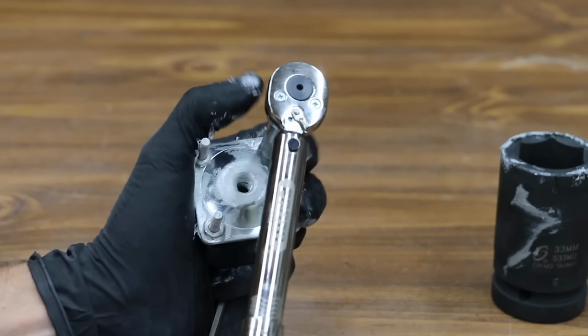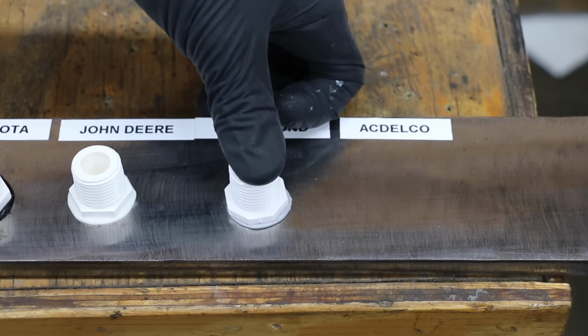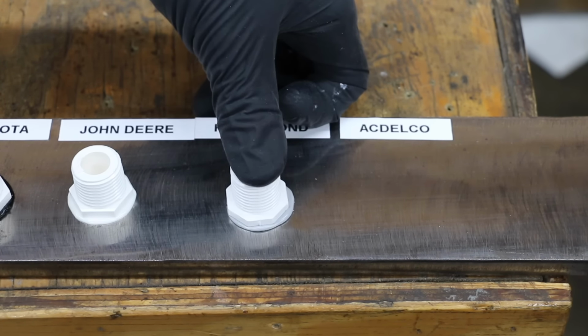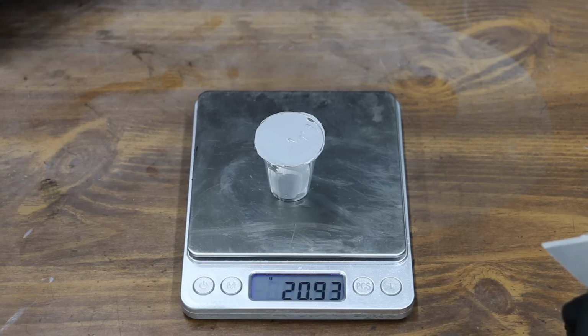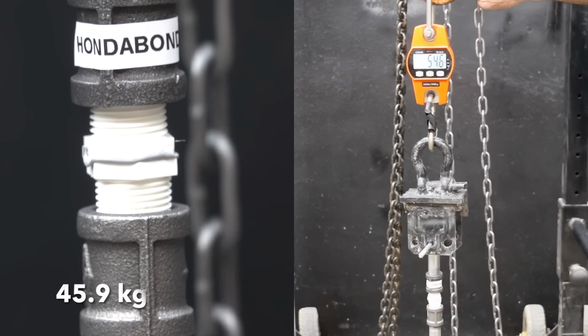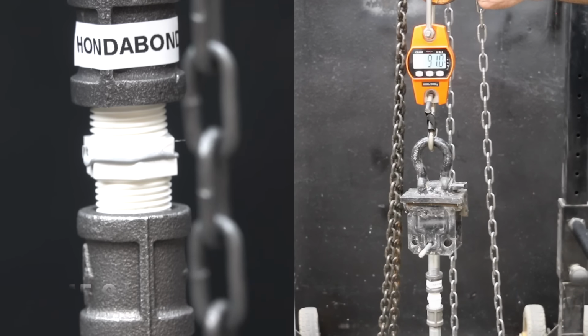The surface layer will dry in about 60 minutes and the film sets to a rubber-like consistency in 15 to 16 hours. And the Hondabond weighs 20.93 grams. And the Hondabond is off to the best performance yet at a very impressive 101.2 pounds.